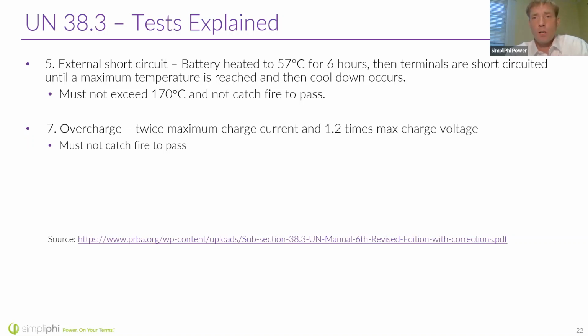Then there's an external short circuit test. In this case, we heat the battery up. It's heated for 6 hours. I don't know a lot about this test, but it's heated up. And then we short circuit the battery and make sure the battery is not going to go into thermal runaway. This would not work for cobalt-based chemistries, right? You short circuit one of those batteries, more likely than not, they're going to go into thermal runaway and they're going to catch fire. So this is done, short circuit LFP battery. It still stays below 170 degrees Celsius and does not catch fire. Again, SimpliPhi's batteries have passed this 38.3 test.